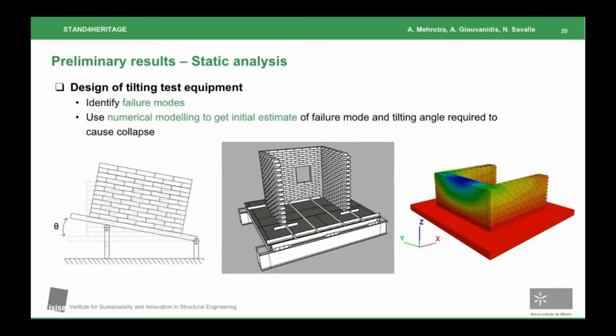Over the past few months, our team has conducted both static and dynamic analyses of different masonry structures. From a static perspective, the team has focused on the design of tilting test equipment. The objective here is to experimentally identify different failure modes of masonry structures through the variation of parameters I mentioned earlier, such as specimen geometry, presence of openings, materials, and connectivity to transverse walls. Additionally, numerical modeling in DEM is also used to get an initial estimate of failure modes of different structural geometries, as well as the tilting angle required to cause collapse.